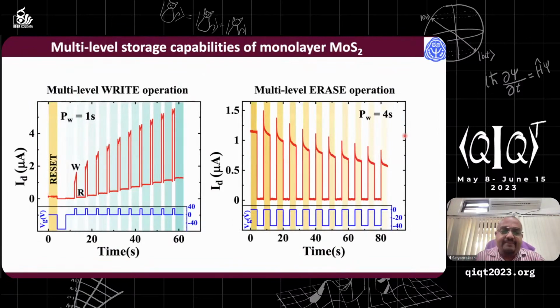Now, taking this as an advantage of memory, what we have done is reset the system first, then apply a voltage pulse of around 30 to 40 volt. And you see what is happening as you increase the pulse voltage, as the pulse train is applied to this material or device. Look at the read current. The read current keeps on increasing.